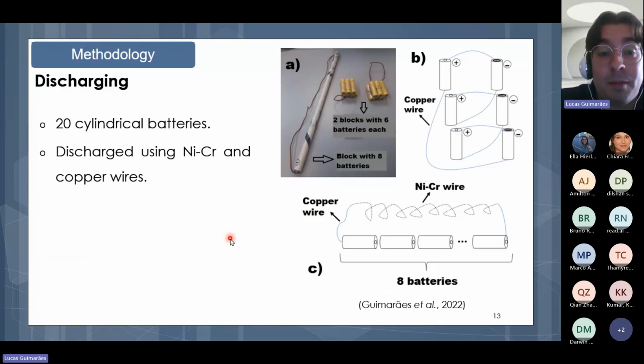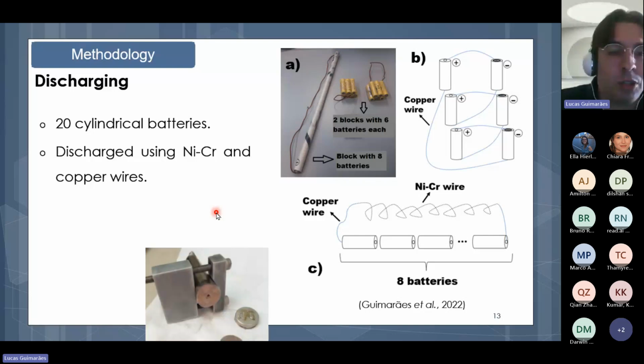For the discharging method, 20 cylindrical batteries were discharged using nickel-chromium and copper wires. These wires close the circuit and then bring the voltage to 0 volts. This method is better than the one commonly used in the literature, which is the use of salt solutions, because using those wires we avoid losing material, for instance the solution, and we also avoid changing the original composition of the battery later on. So it was a better methodology.